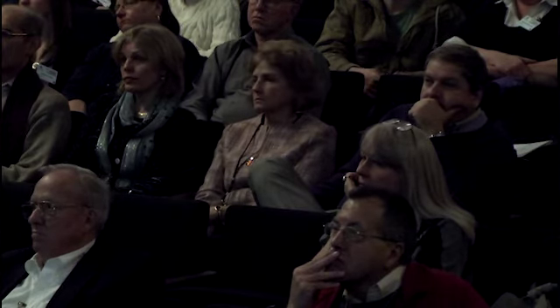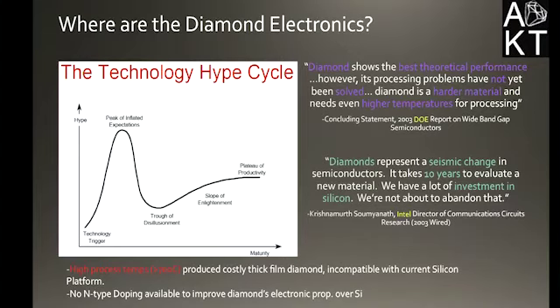Essentially, there's two things that need to be done in diamond, and that is to lower the processing temperatures to allow it to be CMOS compatible, or at a low enough temperature where it can be incorporated with silicon technology and process technology. And N-type doping in diamond has been a major issue, where we can't make diamond conduct in a way that would allow you to shift away from the silicon technology and allow you to further this device development.